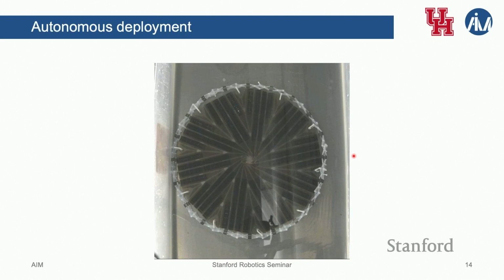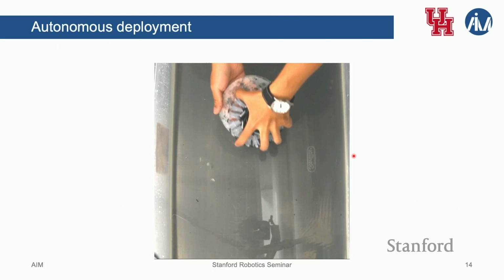And so again, two things to keep in mind: we fabricate it in this state. So this is the energy-free state. The state when I first drop it in, like this one, is the most stressed state. Right, this one, which is a good point, right? Because in the functional state, if it can deploy, it will never break. Because in a sense, the compaction procedure is the most damaging part to the material. Once it compacts into that final state, it will never experience a stress higher than this state.